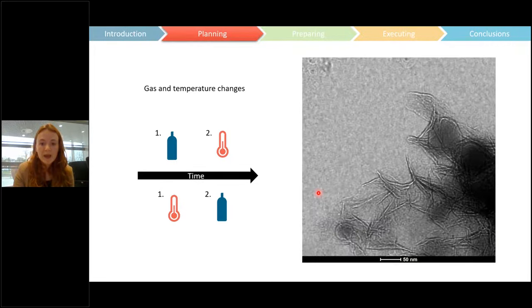What this means for the planning aspect is it's always going to be easier to introduce your gas at a lower temperature and then ramp up from that temperature than it is to start by setting the temperature you want and then suddenly introduce your gas. So it always works much easier the other way around. I would always prefer to introduce my gas at 300 degrees and then ramp to 600 degrees than go the other way around.